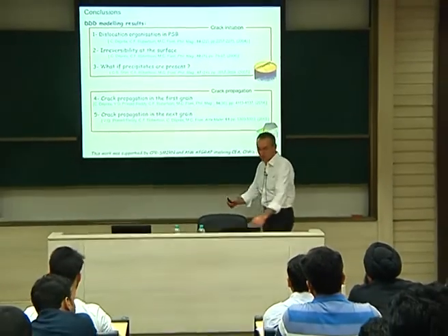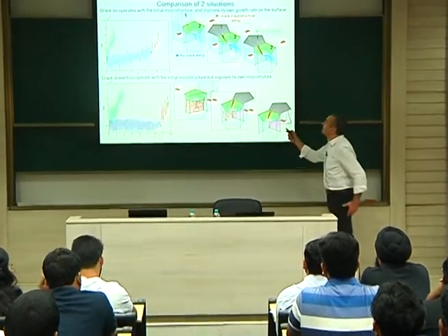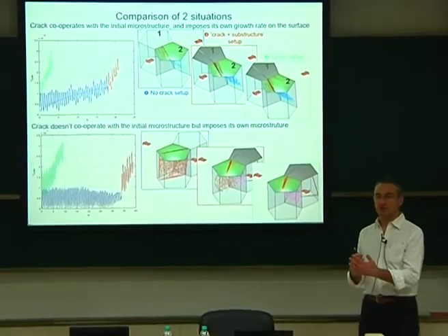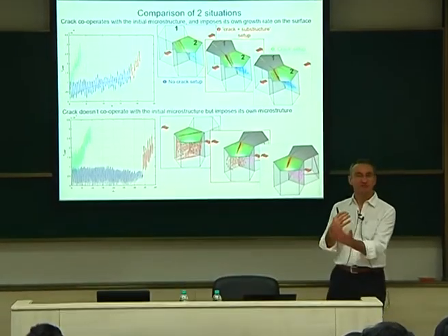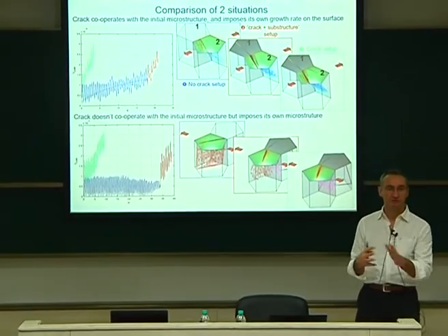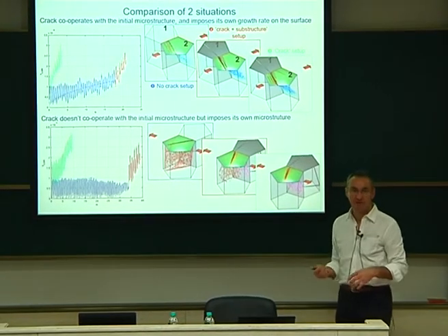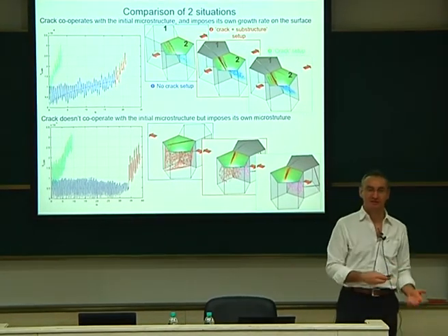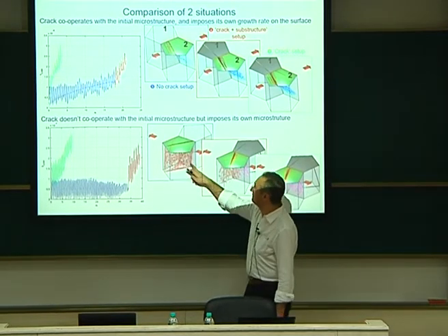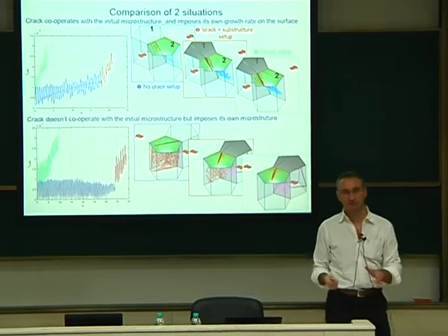Yeah, yes. So you mean with the crack? Yeah. So when we put that at the interface, there is no possibility for the dislocations to cross. It's just like a hard obstacle interface. So we don't care about the plastic displacement at that place. We don't match anything. It's very simple. As I told you, this is simple. We can do a lot better, but I think the result will be the same, except that we'll spend one month of calculation in place of one week. But here, what we say is that at the interface, dislocations stop, as you can see here. They stop and they do not create steps. There is no splitting of dislocations in the grain boundaries. We don't take that into account.